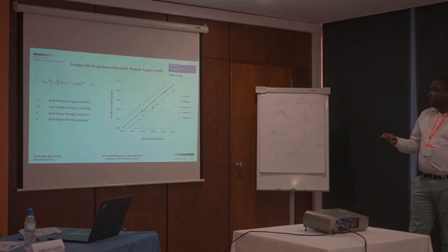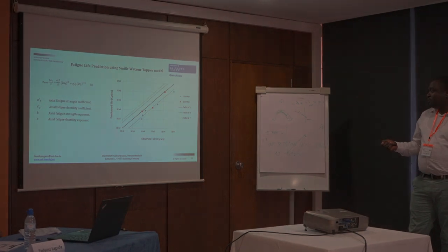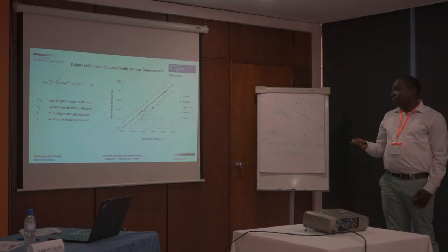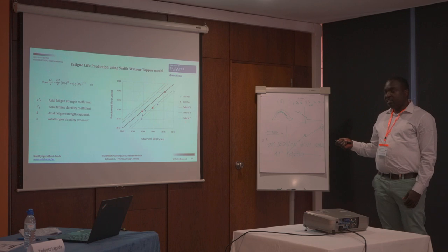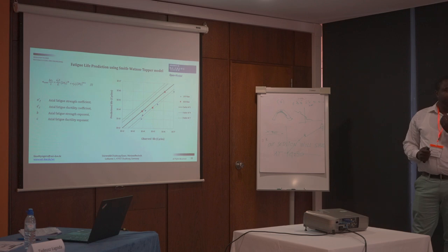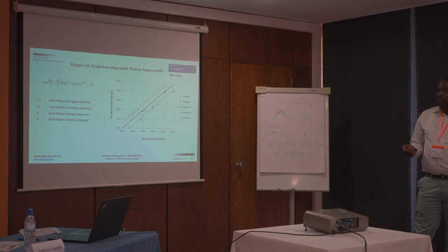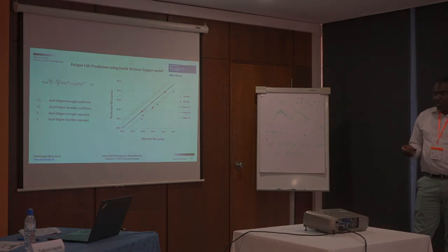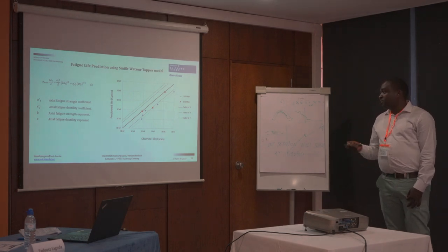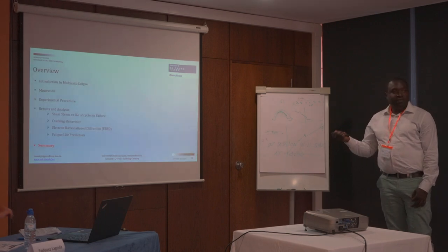And when we plotted that against the observed life cycles, we noticed that the model is underestimating the fatigue life by as much as 7 times. So we believe that this model is not suitable for those situations where there is a presence of static compressive stresses. So next, we'll be applying another model called the Fatemi-Socie model. You've heard about it. It's also another critical plane model. So we are also carrying out more multiaxial fatigue tests and pure torsion tests. So it will be interesting to find out how that model applies for this material and for this type of